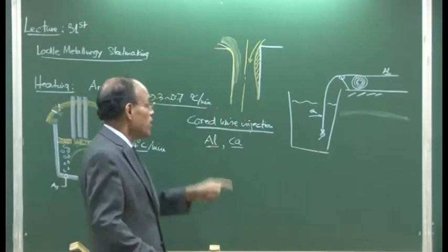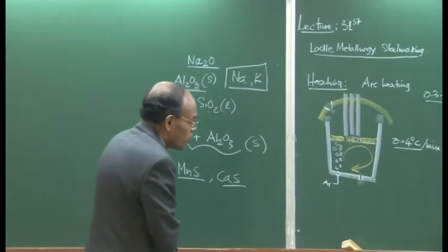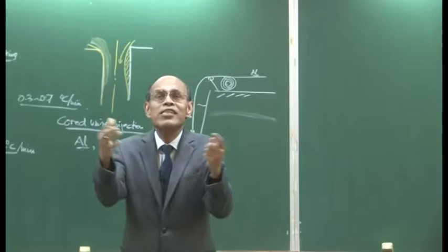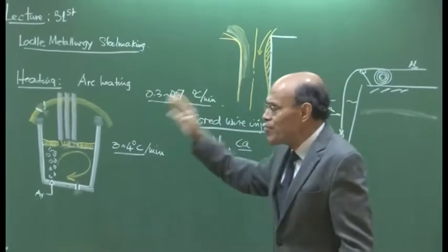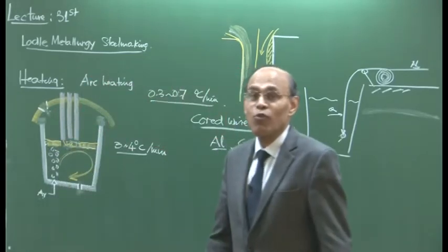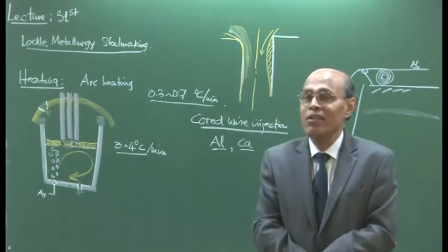to the refractory walls, but we attempt to drain one vessel into another as is experienced during continuous casting of steel. So therefore, in low carbon aluminium killed steel, if you are killing with silicon and manganese, silicomanganese, there is no question of solid deoxidation products. So the problem that I am talking about is relevant to aluminium killed steel, and particularly when you have lower carbon.